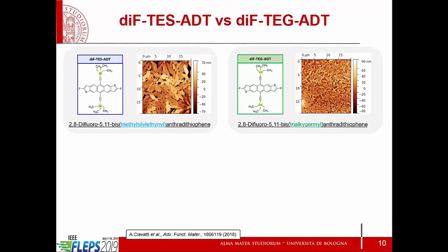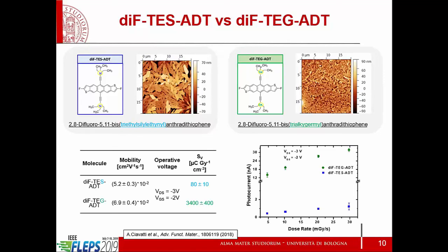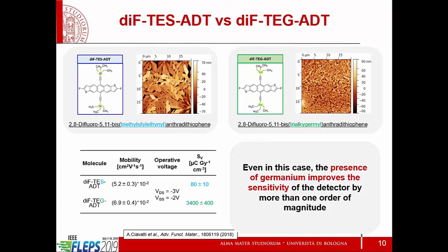We tested, just for completeness, other molecules where silicon and germanium had been exchanged, and here is the result with diF-TES-ADT and diF-TEG-ADT. And you see that you get the same mobility in our thin films, but very, very different sensitivity. So the same films with similar mobility have more than an order of magnitude difference in terms of sensitivity to X-rays, stressing how the swapping of the silicon with germanium is indeed a very important issue. And again, note that here the mobility is identical. So it's not really a matter of charge collection, but really a matter of absorbing and attenuating the X-rays.